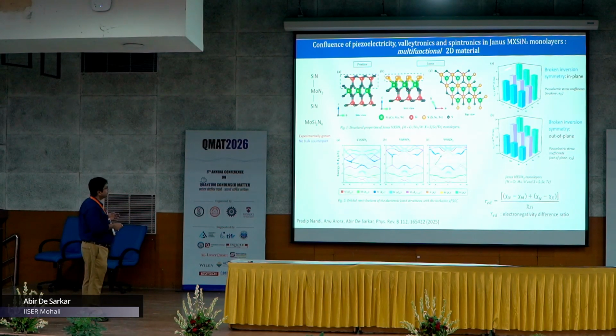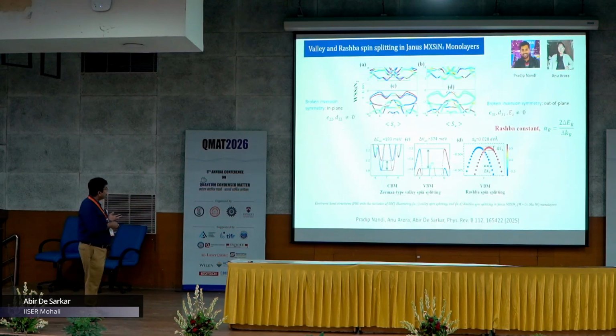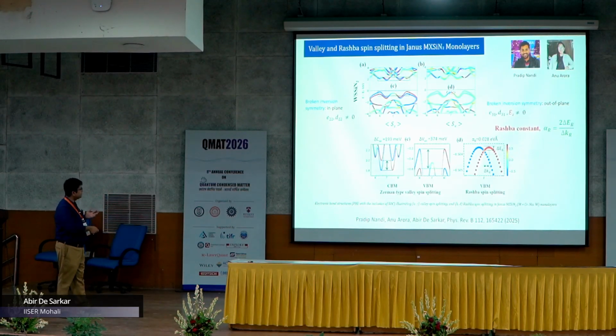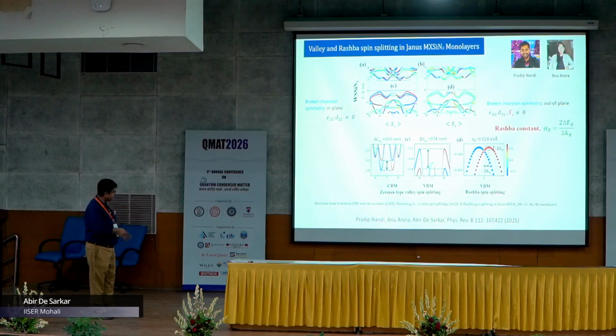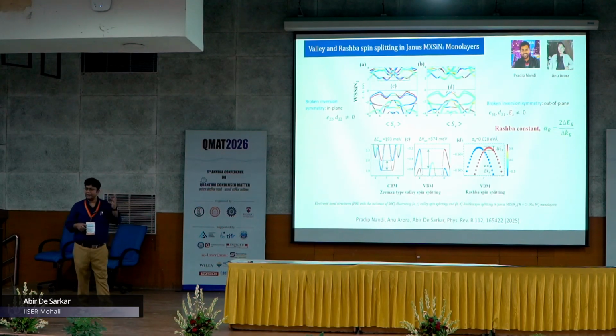So, what we conclude, what we understand here, is that the piezoelectric stress coefficients are proportional to the anionic polarizability to the cationic polarizability, the anionic radius to the cationic radius. Now, as the inversion symmetry is broken in the XY plane of this monolayer, in addition to exhibiting the in-plane piezoelectricity, it also shows Valley polarization. That is what we find. Opposite spins are locked to the momentum values K and K prime, and the extent of the Zeeman type Valley spin splitting is higher in the Janus monolayers containing the heavier elements.